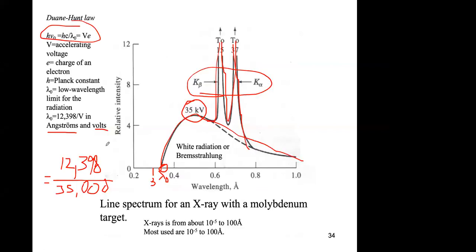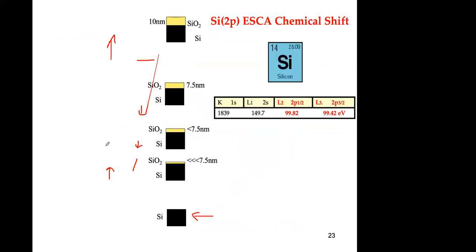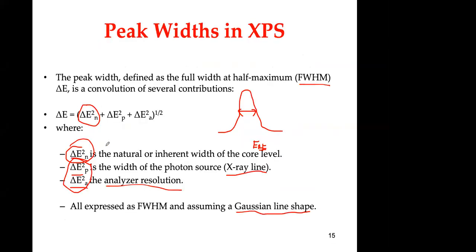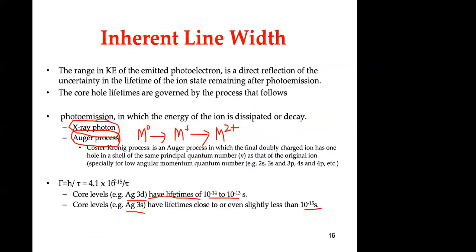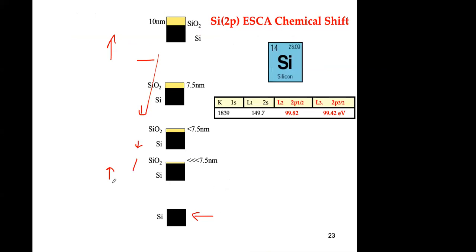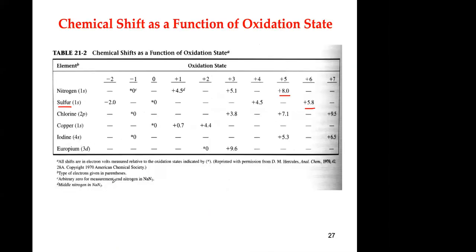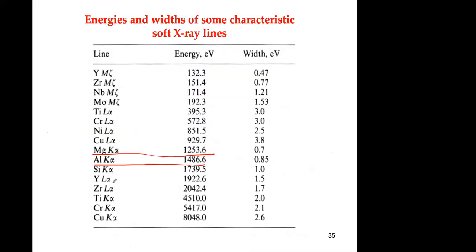One of the things that I mentioned, I'm going to go back a little bit here. Remember that I mentioned that in order to have a narrower peak, a narrower full width at half maximum, you need the X-ray source to have the narrowest delta E. And if you look at the delta E of the natural emissions, these are the full width at half maximum of the emission. This is 0.47. So this would be ideal, 0.47, it's very small. So why don't you use yttrium?